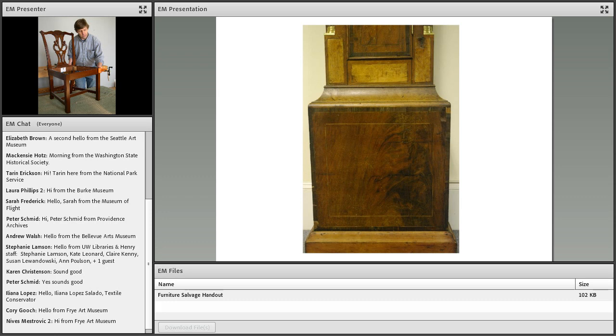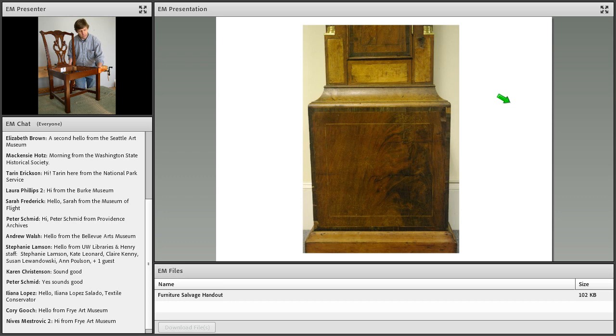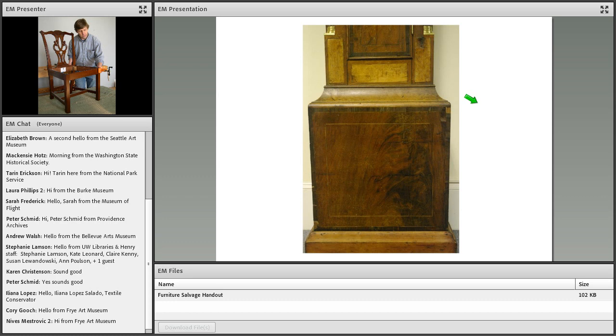Now let's take a closer look at the bottom panel where most of the veneer damage occurred. Here's that bottom panel, and you may notice a couple of horizontal cracks. Those would be here and there's another one here. These are very old cracks, and you can tell that because the cracks are dark and they have darkened with age. If these were new splits, you would expect to see fresh or light colored wood along the edges of the cracks.